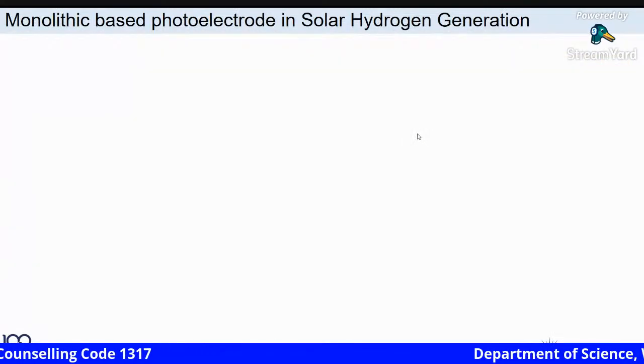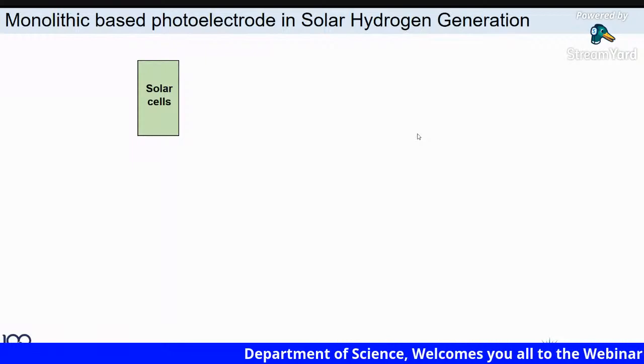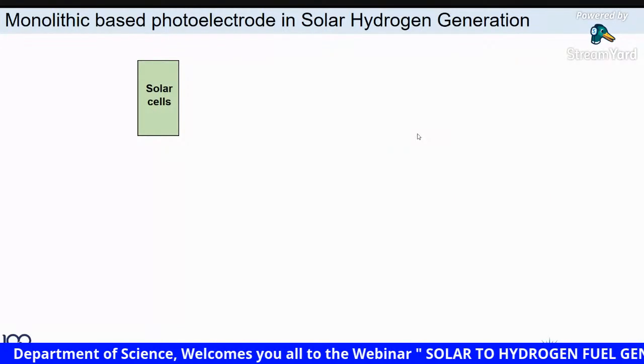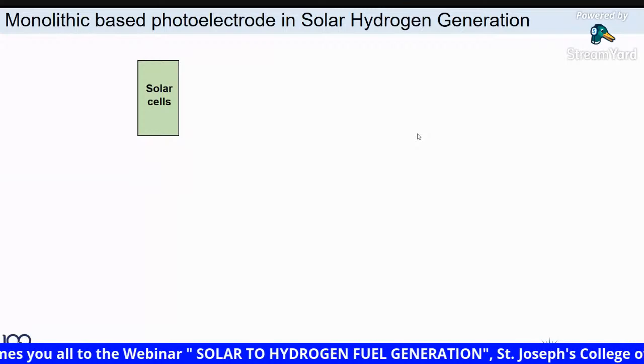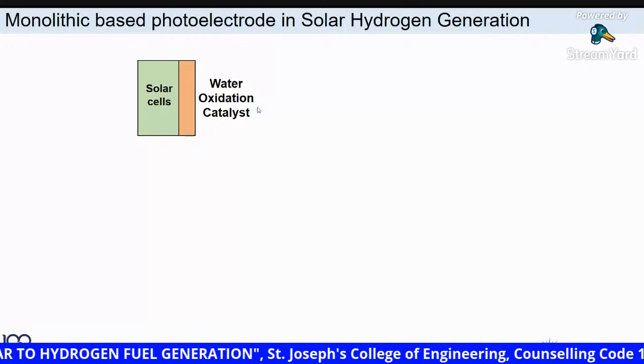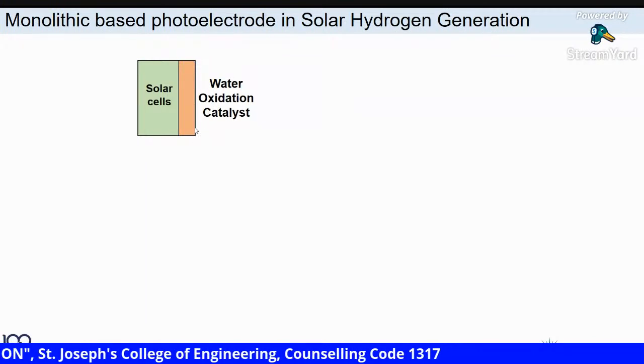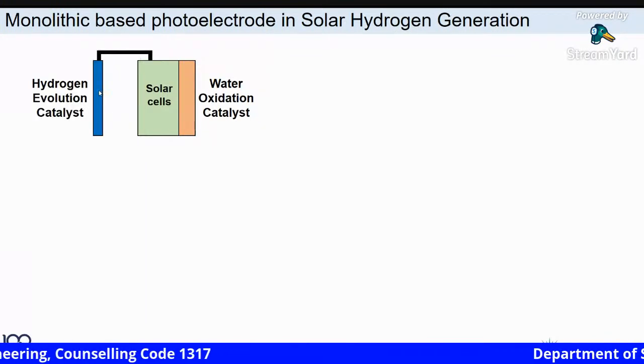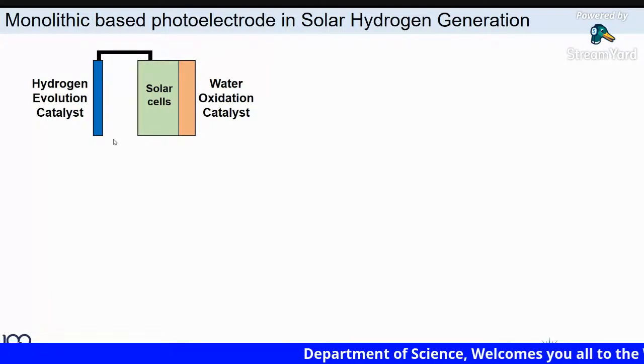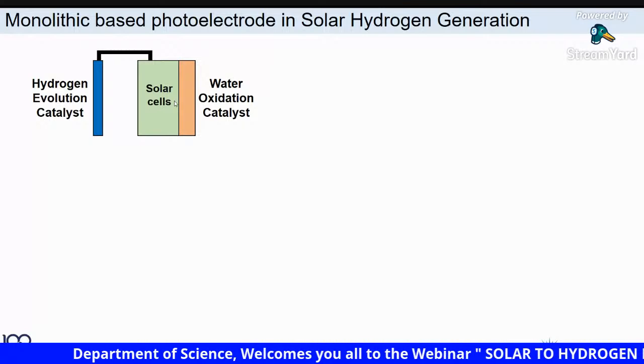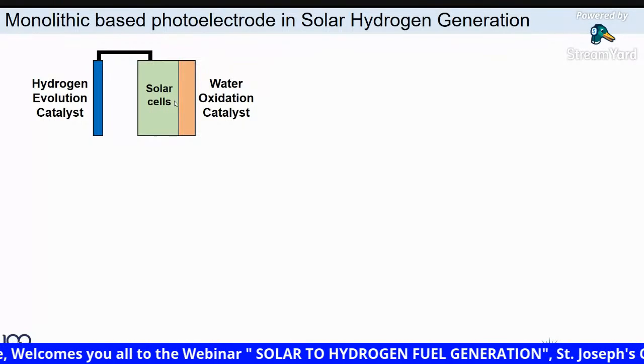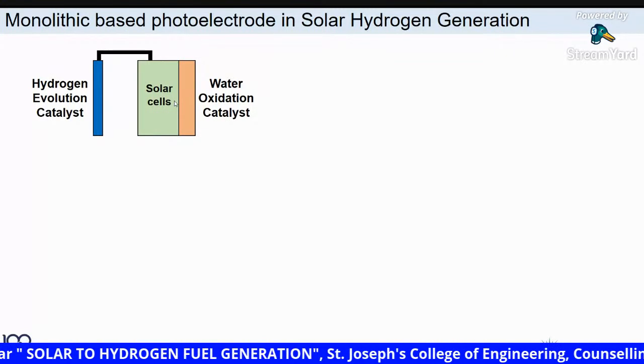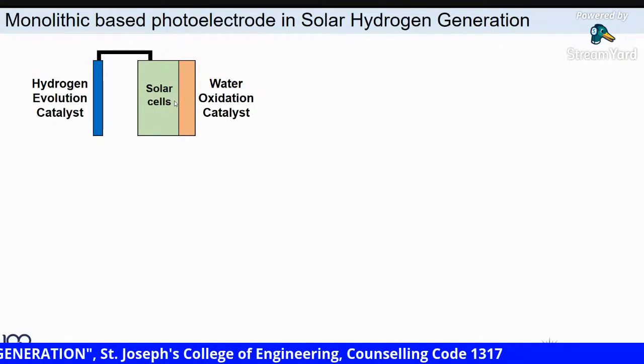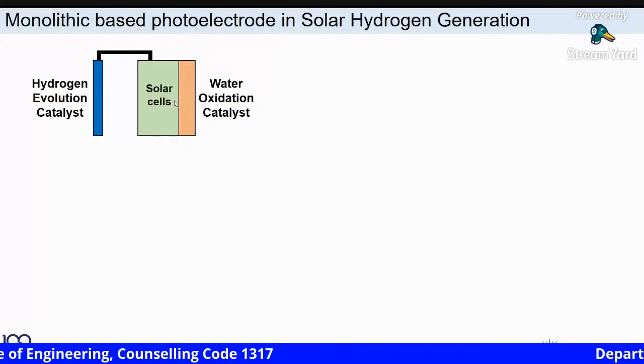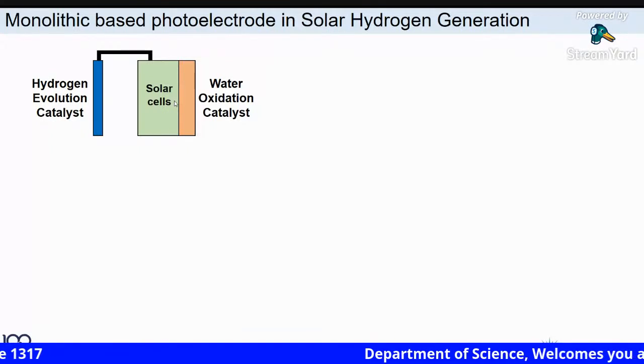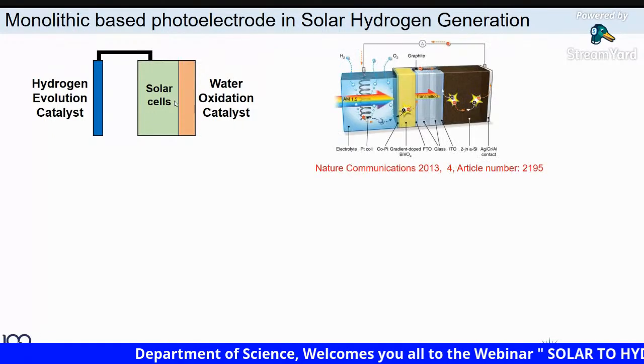Okay, in recent days, a new type of architecture is emerging, instead of the photoanode and cathode shown separately. So now they are applying solar cells directly, and then they coat a water oxidation catalyst on one end, and they connect as usual the platinum cathode. They put it in a water splitting cell. So why did they introduce the solar cell? Solar cells have a high efficiency from the charge separation point of view, as well as light absorption. So this will help to drive the water splitting reaction more effectively than the direct photoelectrocatalysis process directly on the electrode. Okay. This is another example.